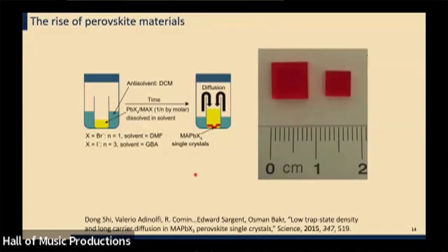Another thing when we in our group got early into this field, I guess this is about 7 years ago, is that these materials seem to like to be pure. They seem to like to not have sites, defect states within their band gaps, where electrons and holes can come together and can recombine and lose energy. But instead, they seem to like to clean their own band gaps and ensure that between the conduction band edge and the valence band edge, there is a very, very low density of what are called deep electronic trap states.